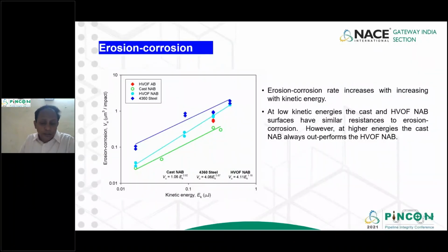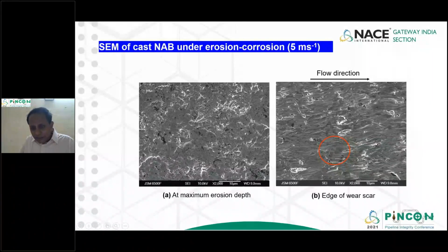Then we come to erosion corrosion. Here, similarly, I look at the cast NAB. At lower kinetic energy it is almost close to the thermal spray process HVOF NAB. However, as usual, the erosion corrosion rate also increases for the coating material compared to the cast NAB. The base 4360 steel is actually very much higher. And also we can see, this is actually very particular. If you zoom in, these are the phases.